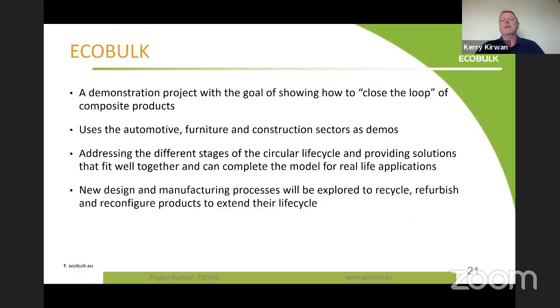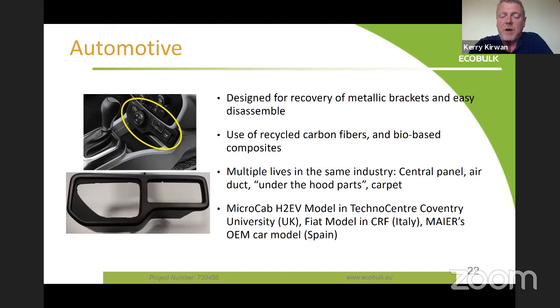And what we're actually doing, as I say, is trying to get real circularity with some of these composite materials. So within the automotive one, again, we've got some recycled carbon fiber and the bio-based composites I just spoke about there. We're using them, and we're making trims and fascias and under the hood parts. And there's some specific models that you can see down the bottom there, where this is being put into limited volume test run production lines. So Fiat, one example, and they're again performing very, very well in situ, and we hope they will become standard issue over the next few years.